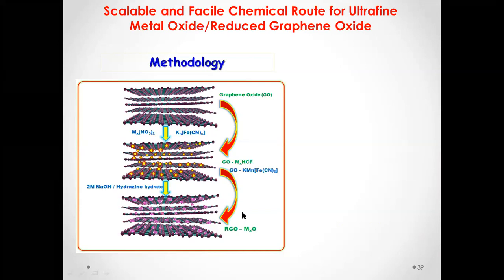So here what we have done is we took graphene oxide, and we put some metal nitrates and potassium hexacyanoferrate complex on this. We will form a metal hexacyanoferrate complex on these graphene sheets. When you put these graphene sheets in a strong KOH solution, potassium hydroxide or sodium hydroxide solution, it will immediately get decomposed into metal oxides. Not only metal oxide, crystalline metal oxide without any heat treatment.